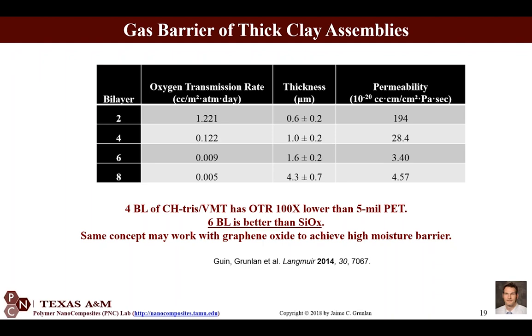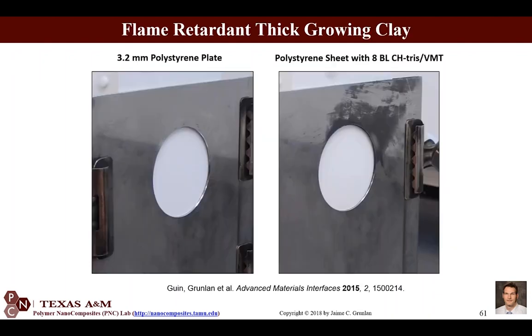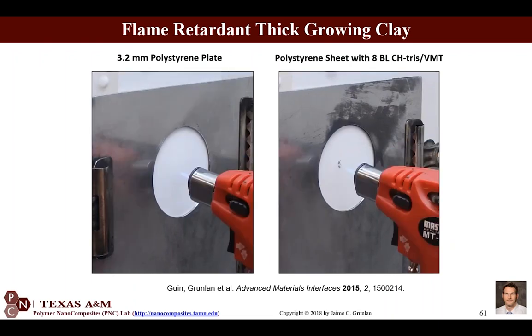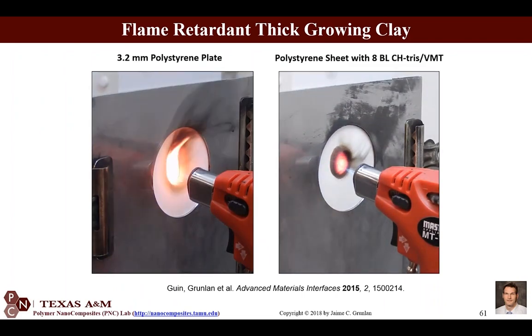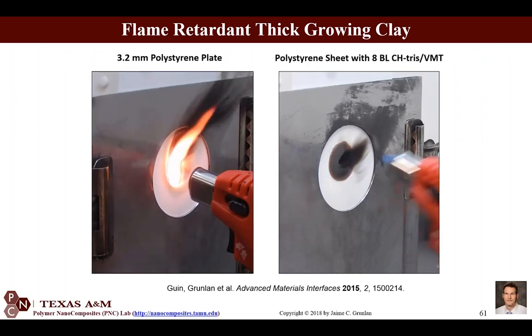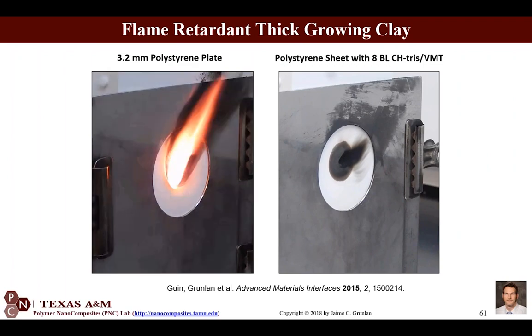And we have a number of other tricks we can do too. So this is just highlighting one example. It turns out that as a segue to the other, much shorter part of my talk, in this case, we took a 3 millimeter thick polystyrene plate, and on one of the plates, we actually put an 8 bilayer thick layer by layer assembly, and you already saw the video there.